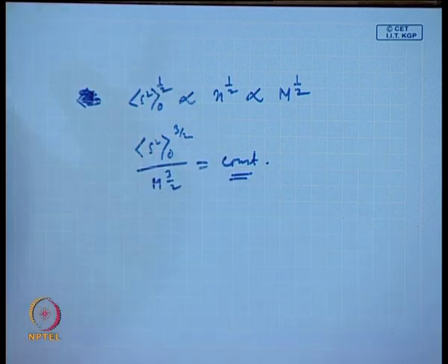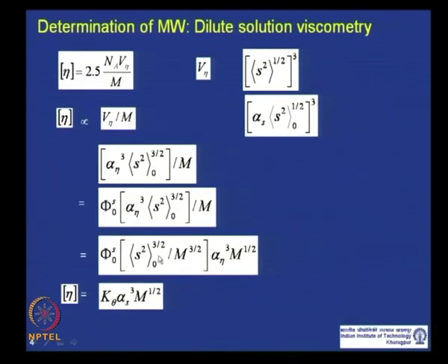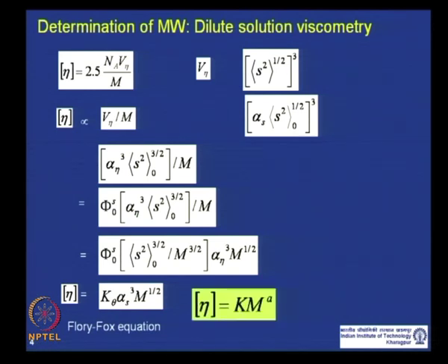So, what we are doing here, this is a constant as we just discussed, this is also constant, and we are clubbing these two in another constant, and you have the expansion factor and molecular weight to the power half. This expression is known as the Flory-Fox equation.